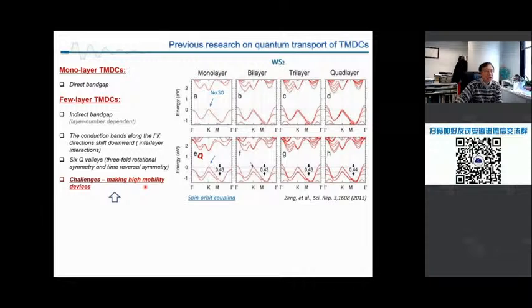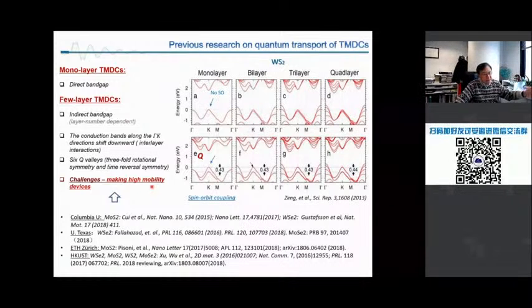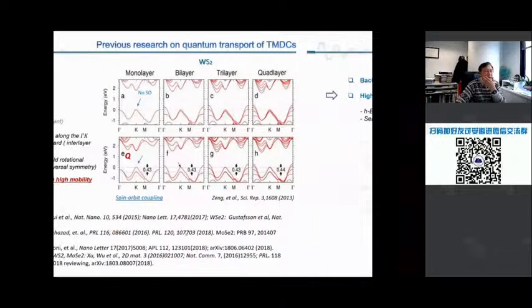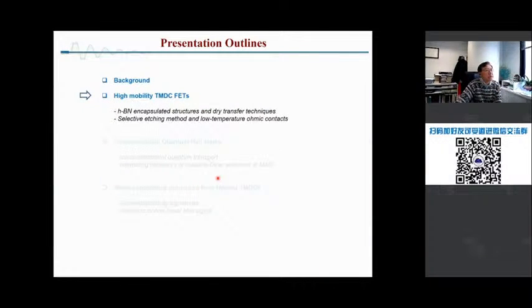All right, so the challenge to measure the states through transport is to make a high quality device. And in the past 5 years or so, different groups have made a great contribution to probe the quantum states in these materials. And next, I'll show you the very fundamental things, how to make a high quality device. Okay. So I'm going to introduce these encapsulated structures with boron nitride, because boron nitride is an ideal dielectric material, using so-called dry transfer techniques. And then I'm going to demonstrate our unique technique we call selective etching or phase transition to make an ohmic contact.